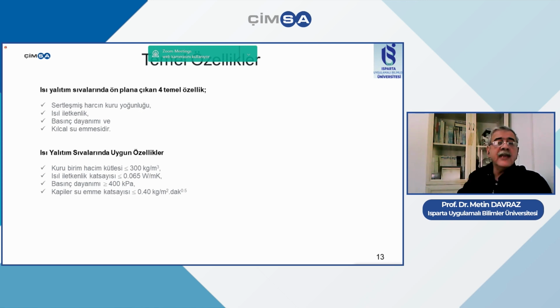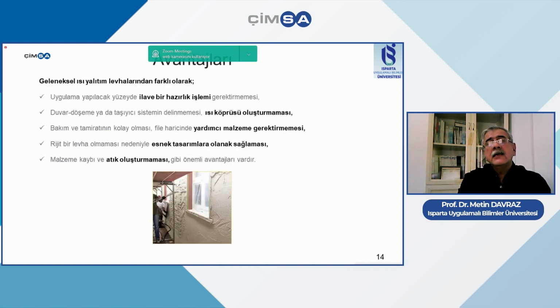And of course, when we look at this plaster type, the dry unit volume rate is 300 kilogram per meter cube. And when we look at the heat conductivity, its coefficient value is 0.065, and the pressure resistance is 400 kilopascal, and capillary water absorption coefficient is, as you can see.